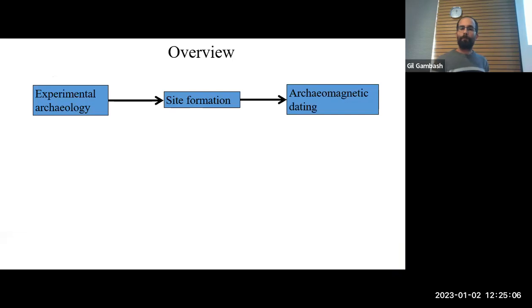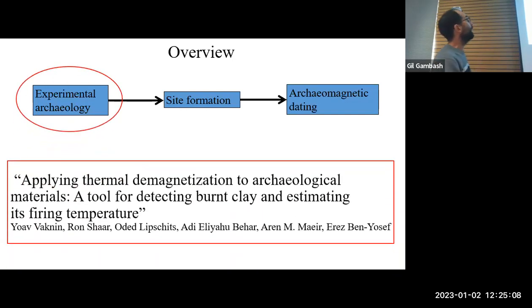So I'll start with talking about the experimental archaeology, what we did. This is a paper that's now under review. We show how we can reconstruct the firing temperature and identify fire with burnt clay archaeological materials using thermal demagnetization. Thermal demagnetization is when in the lab we measure the magnetic field and then we gradually erase it by heating it in an oven with a zero field environment.